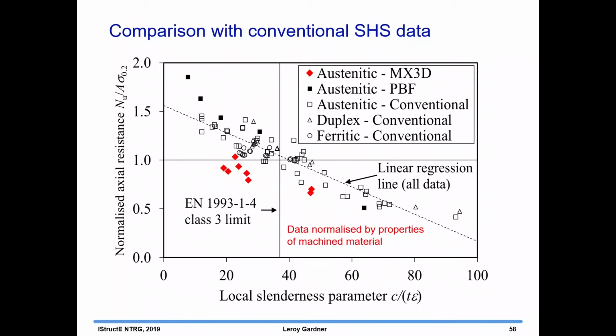And then here are the results for the 3D printed material. So it's a similar trend, reducing normalized capacity with increasing slenderness, but it is clearly a bit lower than the existing data, reflecting the higher imperfections and so on. And we would need some sort of lower bound in order to think about design of these things. But by and large, the components behaved in a similar way to conventionally produced material.